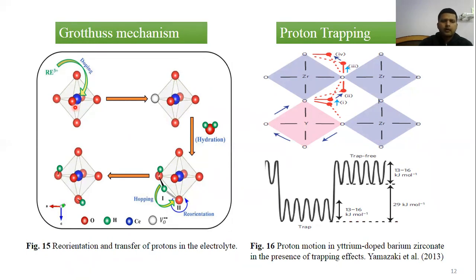Upon doping with rare earth at the B site, we create oxygen vacancies, and upon hydration, the water molecule settles at the oxygen vacancy, and the hydrogen atom gets loosely bound and starts to reorient in the surrounding oxygen lattice, thereby leading to proton migration by reorientation and hopping. This complete mechanism is known as Grotthuss mechanism.